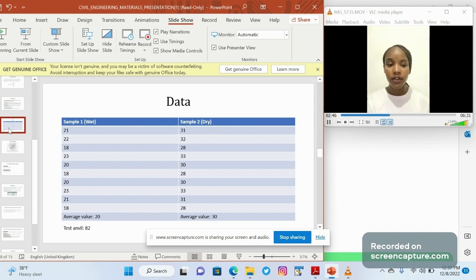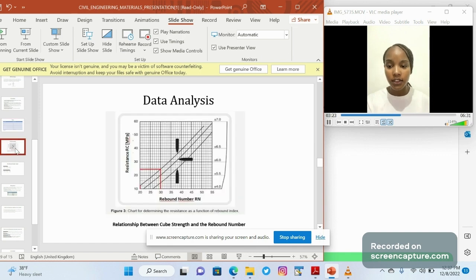After averaging the values that you got, this is the data that you obtained. The average values obtained were 20 rebound number for the wet concrete cube and 30 rebound number for the dry concrete cube, and 82 was the value obtained from the test anvil as we calibrated the rebound hammer. There was a graph that we drew. Since the test was done on the top of the concrete cube, the top line on the graph, among the three lines, was considered, and after plotting,